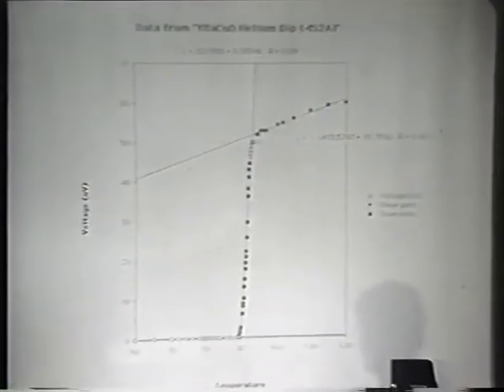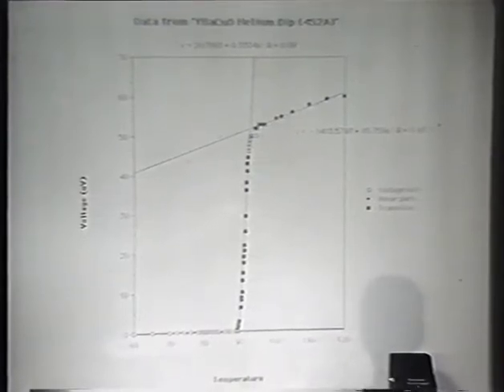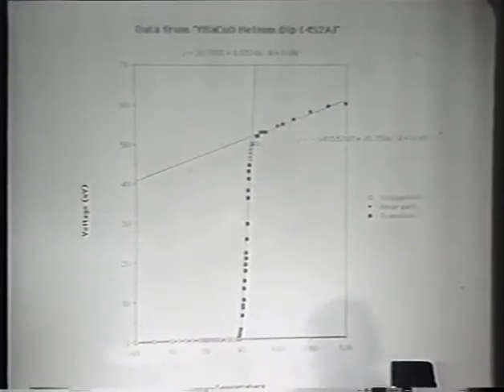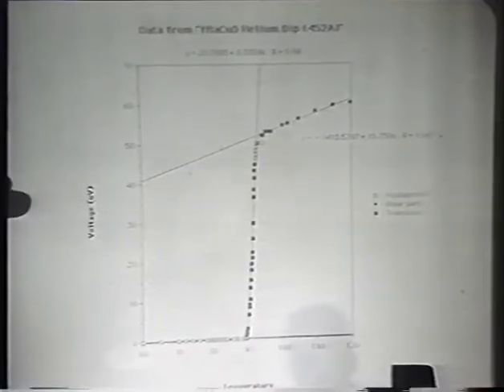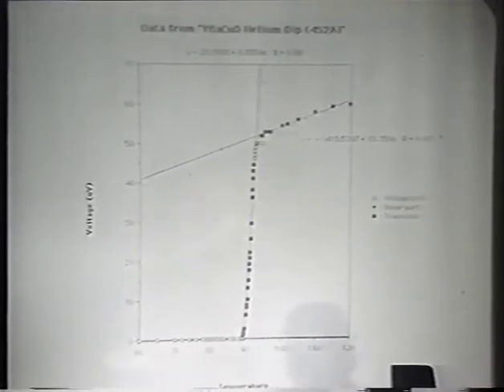Our resistive transitions look pretty much like the ones you've seen many times tonight. If we fit straight lines to the resistance versus temperature, we find that the resistance doesn't extrapolate to zero at T equal to 0, but the transition width is very narrow, approximately 2 Kelvin, with zero resistance at about 90 Kelvin.